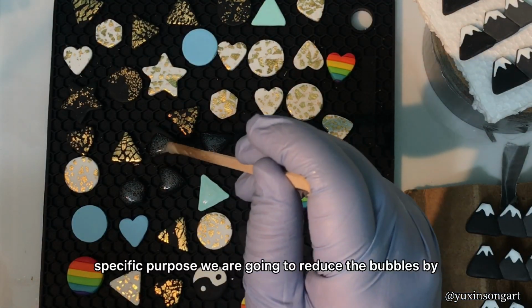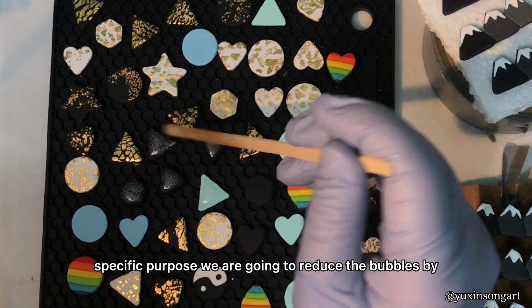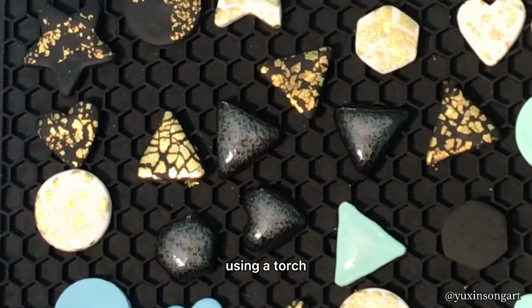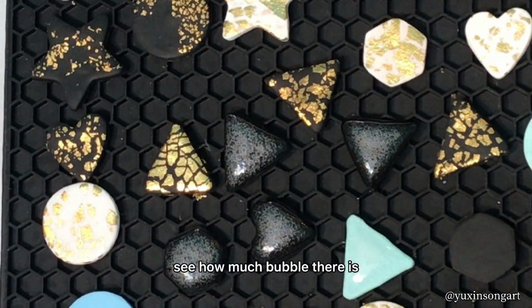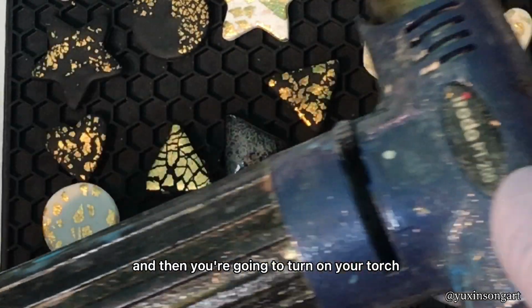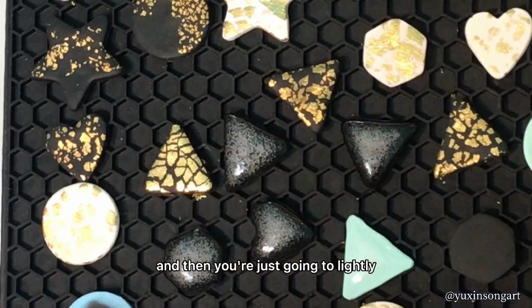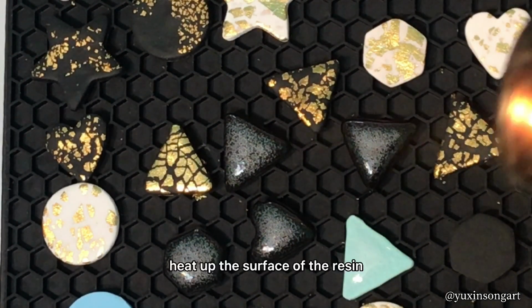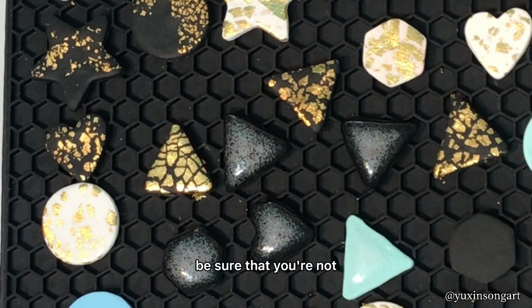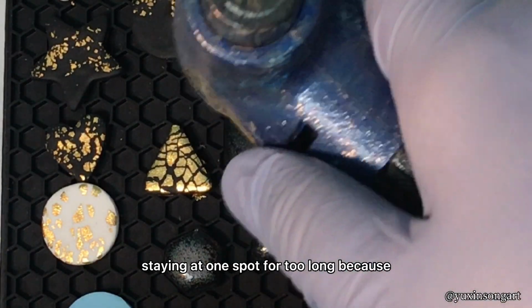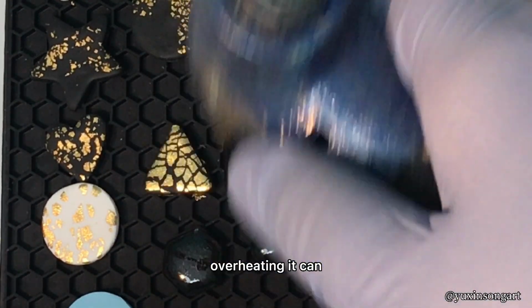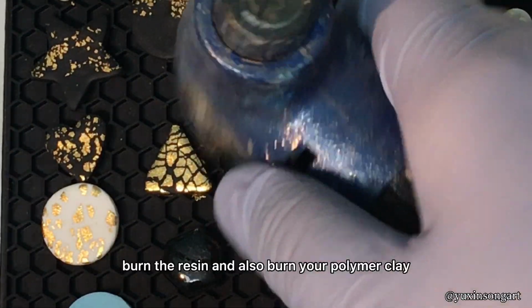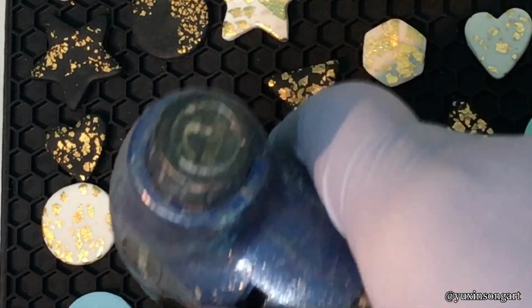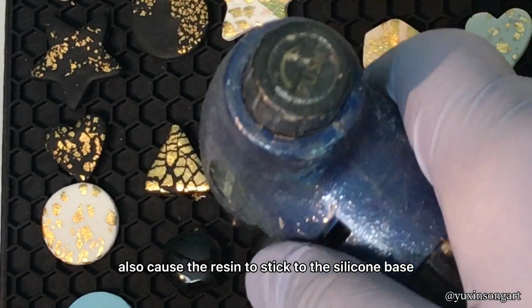And for this specific purpose, we are going to reduce the bubbles by using a torch. See how many bubbles there are? There is a bunch, and then you're going to turn on your torch, and just lightly heat up the surface of the resin. Be sure that you're not staying at one spot for too long, because overheating can burn the resin and also burn your polymer clay. Overheating can also cause the resin to stick to the silicone base.